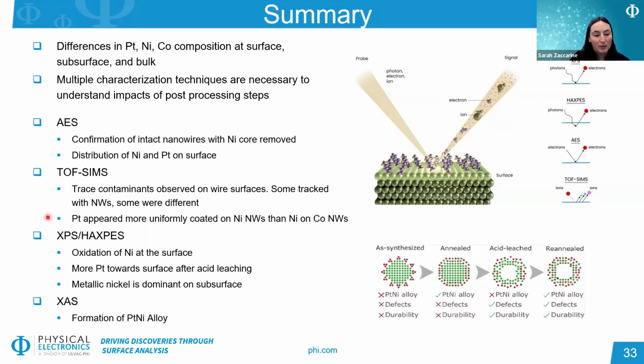And we also saw, comparing the platinum nickel data set to the platinum nickel cobalt data set, that the platinum coating on the nickel nanowires was slightly more uniform than the nickel coating was on the cobalt nanowires. Going a little bit deeper into the sample with XPS and particularly HAXPES, we saw that there was a lot of oxidized nickel towards the surface, more platinum to the surface after acid leaching, and then we saw more metallic nickel the further that we analyzed deeper into the sample. And this was able to track with some of the results we saw from the bulk XAS technique that showed differences in the platinum nickel alloy content.